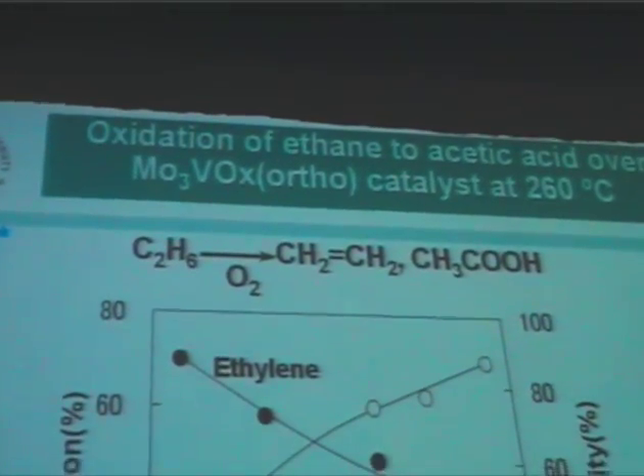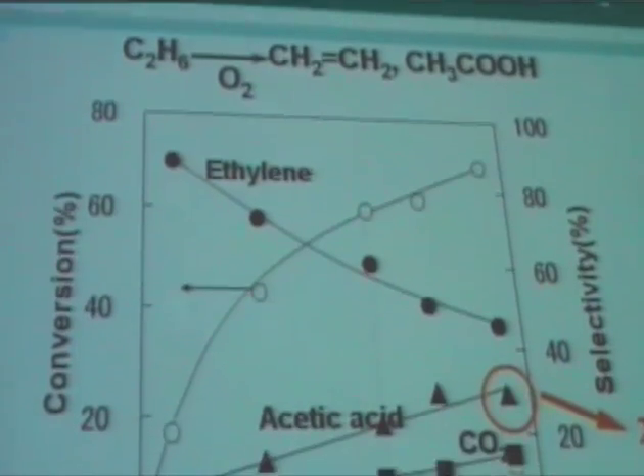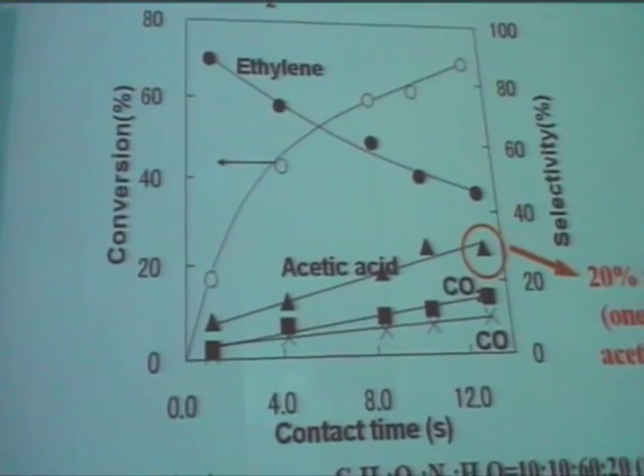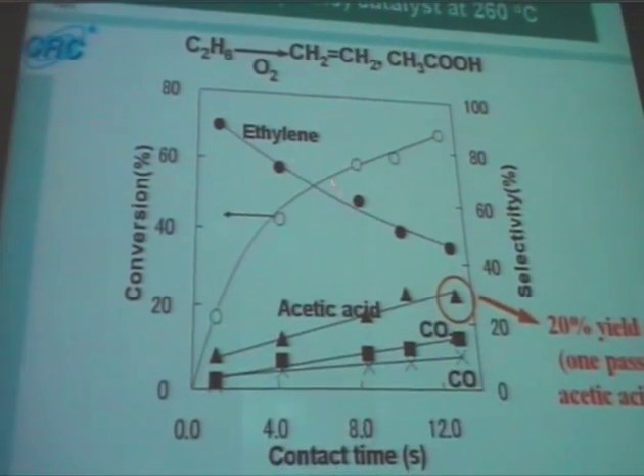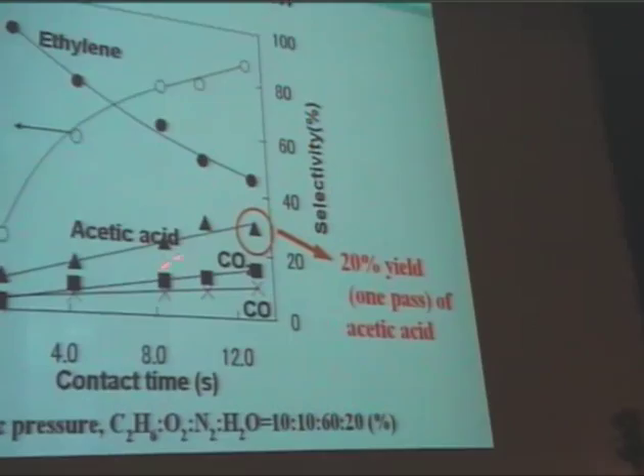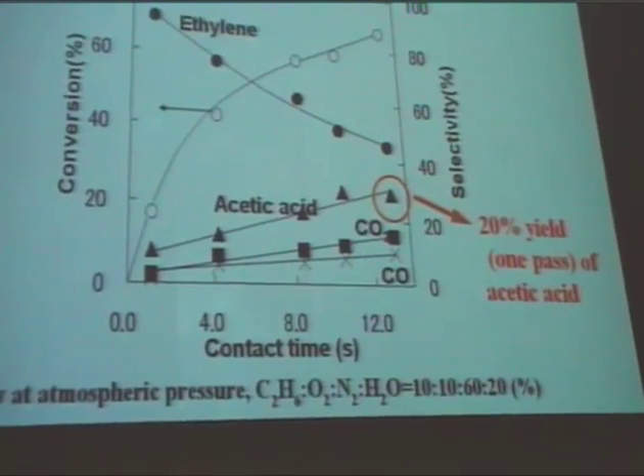This is a very practical catalytic application — a typical example for ethane oxidation to acetic acid at 260°C. Normally, for ethane oxidation there are many types of solid-state oxidation catalysts, but normally it works at more than 500°C to give a reasonable conversion of ethane. But it works at very low temperature, and the conversion is here 70% — that's quite high. So the selectivity for ethylene is at the beginning quite high, and then it goes down, and then you can get acetic acid. Under these particular conditions, you can achieve a 20% yield of acetic acid.